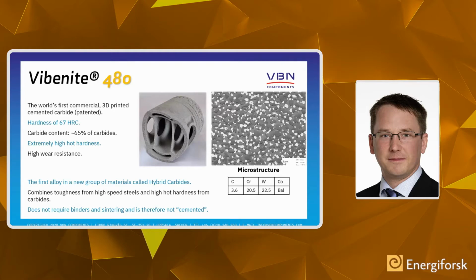Vibenite 480. This is the world's first commercially available 3D printed cemented carbide. And we have another idea behind this, because this is not a cemented carbide, but it is in the range of cemented carbide. Because we do not cement it, we don't have any sintering or binding process as you have in traditional tungsten carbide cobalt grades. So we have done this from pre-alloyed metal powder and EBM technology.